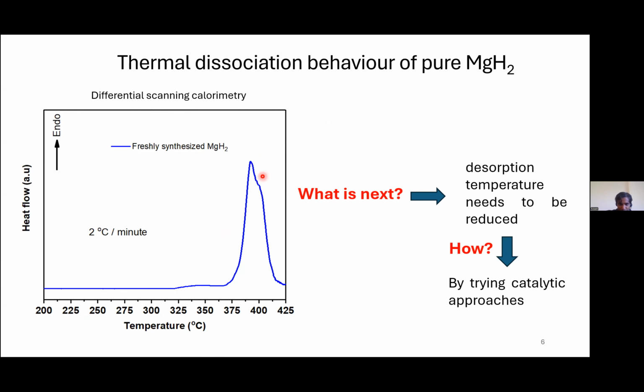As you can see, pure magnesium hydride endothermically discharges hydrogen almost closer to 400 degrees centigrade, 375 is the onset temperature, but it's a very high temperature. What is the temperature at which our gasoline vehicles operate? It's room temperature. Gasoline is obviously a chemical. It combusts at room temperature. So anyway, for a chemical to react, you need a temperature. If this chemical shows a temperature of 400 degrees centigrade, what is offered for our vehicles? So the question is, what is next?